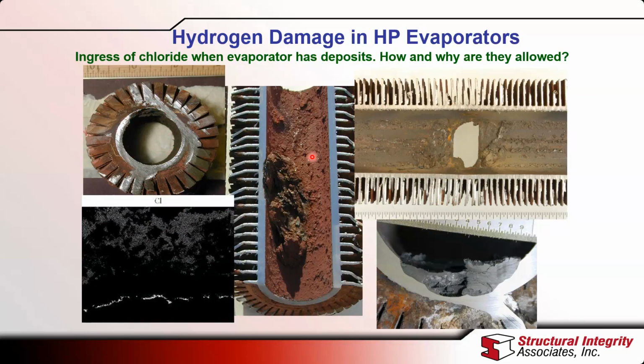You cannot have hydrogen damage or under deposit corrosion unless you have these heavy deposits. The failures that occur are usually similar to this, like a little window or a thick edge failure takes place. And this is a result of having this corrosion take place. You can see the corrosion here eating its way through the wall of the HP evaporator.